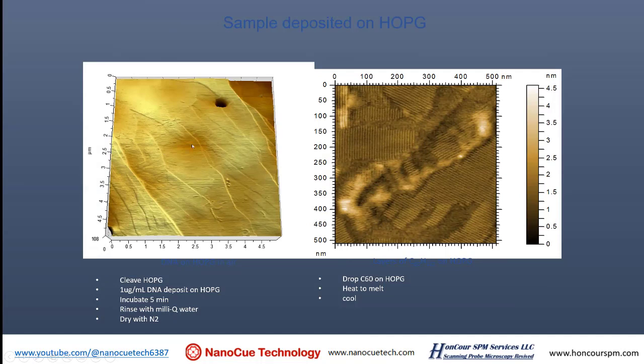Okay, atomic steps are very useful. They're not just some kind of defect of the sheet on the surface, because if you see something that is totally flat with nothing on it, sometimes you cannot tell. You don't have an image, or you don't have anything to see. But if you see an atomic step, that's great, because now you know your instrument is working. And second, if you see a step, you can measure how sharp the step is. That's because the atomic step is atomically sharp. It's one atom wide.